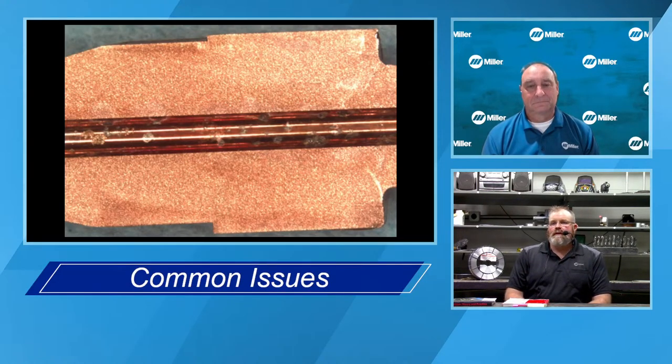As we're welding, that welding current gets to the wire. Those peak amps and welding current are all getting to the wire through that contact tip. And that wire is constantly rubbing on that contact tip. As that power transfers from the contact tip to the wire, sometimes you might get a little intermittent contact in there, and you might have what we call micro arcs inside. That's what you see, those little spots inside that contact tip called micro arcs. That's the erosion actually happening in your tip.